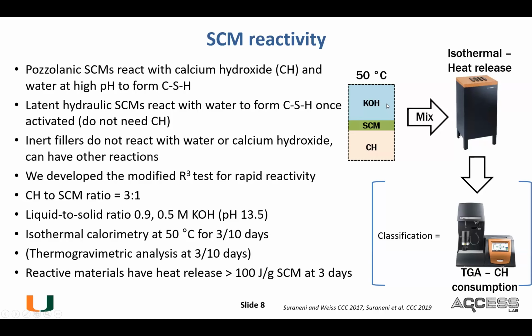On the other hand, supplementary cementitious materials, or SCMs, they do something. They actually have other reactions, not the same as the cement reactions. But because of that, if you put 40% of an SCM, the strength reduction is not 40%. In fact, at later ages, it's probably closer to 10 or 15%. At early ages, it's a little higher.